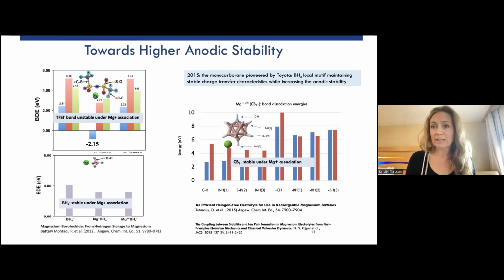And we did the same analysis on that anion. And again, it has the same conclusion as the monocarborane: looking at all the different bonds present in that molecule, they're all stable, even if you expose it to magnesium 1 plus. Okay, so we think we have a computationally accessible metric for stability.